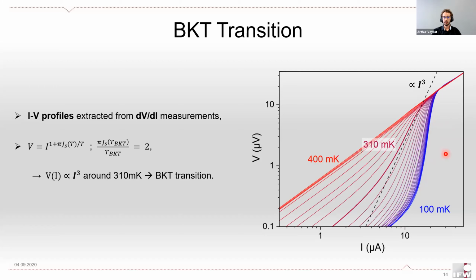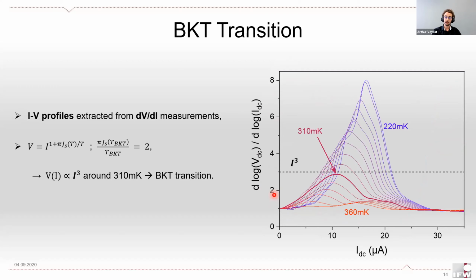And according to the BKT model, if we have a BKT transition, at the BKT temperature, we should find a power law of order 3, exactly. So this is what we find at around 310 millikelvin, but it is maybe not very visible in this plot. For better visibility, we can simply take the logarithmic derivative of the potential. This way, we're directly looking at the exponent of a power law, and we can see more clearly that it is at around 310 millikelvin that the power law of order 3 is reached.